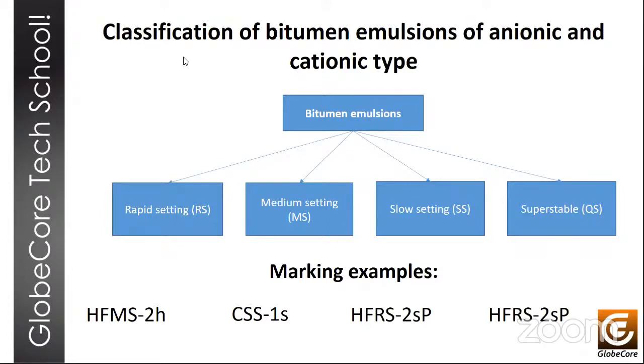First of all, the type of emulsion is indicated by the rate of its breaking or setting. For example, a rapidly setting emulsion will be designated RS. Then either the letter C is put in front of the type of emulsion, meaning cationic, or no letter is put before the designation, meaning anionic. So RS would mean a fast anionic emulsion, CRS would mean a fast cationic emulsion.